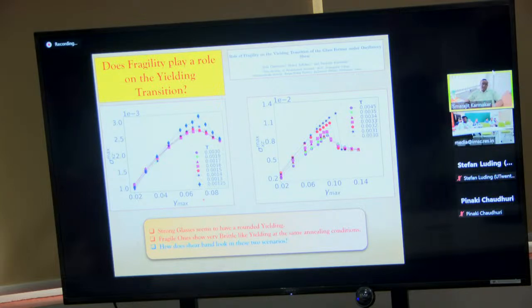What we feel is that the scenario lies in the shear band. If you plot stress versus strain, you see that in a strong glass, even if you have reasonably well annealed glasses, you still do not get very clear-cut shear band-like drops. But for a fragile glass, you get a very clean shear band formation. So we are pushing ourselves a bit more along this line, and we have to simulate much larger system sizes to get a clean shear band and to study whether there is indeed a difference in the shear band between strong and fragile glass formers. We don't have an answer to it yet.